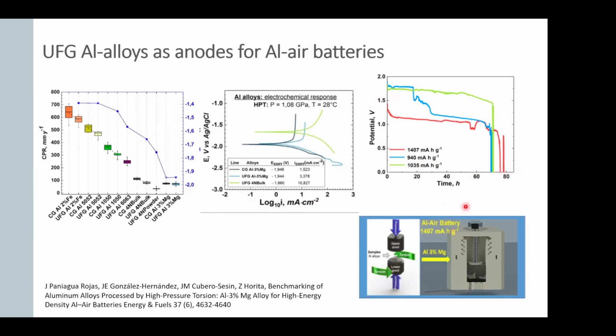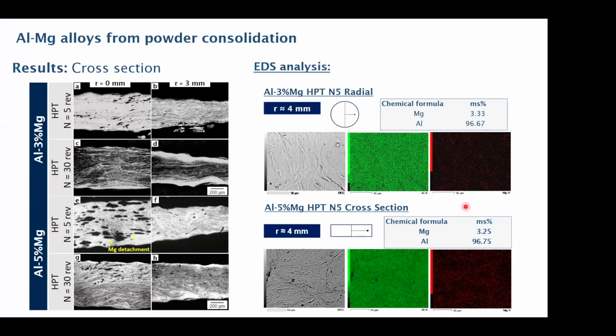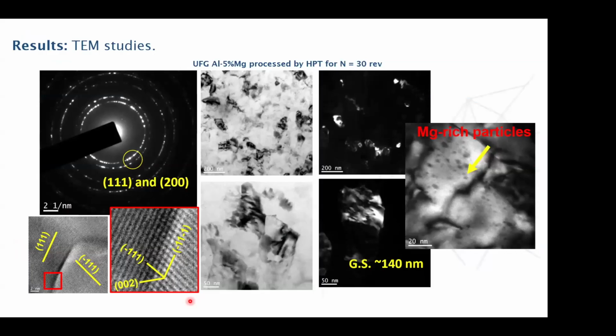And this is one of the works we've been doing, and we've been actually consolidating powders, increasing the amount of magnesium and the amount of strain. You can see here cross sections of discs. This is the center and this is the edge. And what we see is that we can add more magnesium. We can refine the beta aluminum magnesium particles. And then at the edge of the disc, we see fewer of these particles. We can dissolve a high amount of magnesium, 3%, which is kind of the solubility limit.